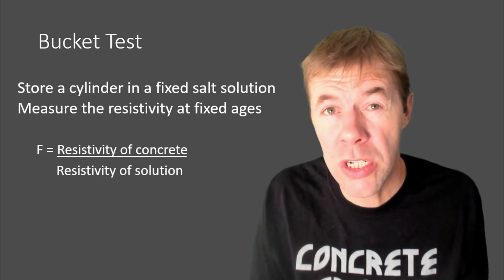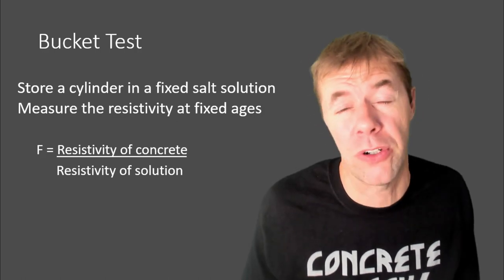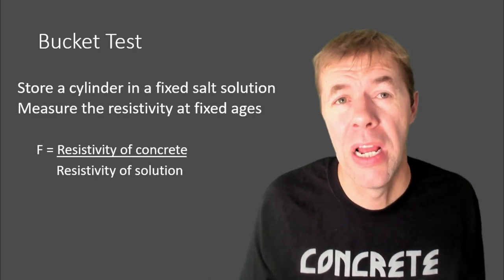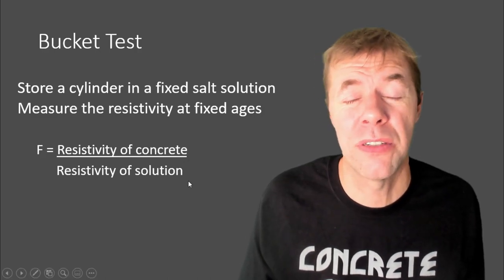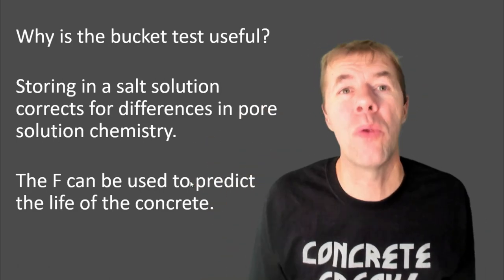It's fixed concentration of salts and measured at fixed ages. And you'll get something called the F factor or the formation factor. It's basically the resistivity of the concrete divided by the resistivity of the solution. Why do you do this? What is it all about?